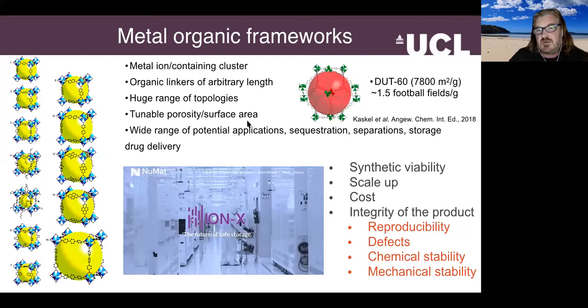And to give you an idea of the surface area of these materials, I think the current record holder is this cryptically named material called DUT-60 from the Kaskel group. That has a surface area of 7,800 square meters per gram. So that is approximately 1.5 times the surface area of a football field in 1 gram of material. So these are incredibly porous materials.